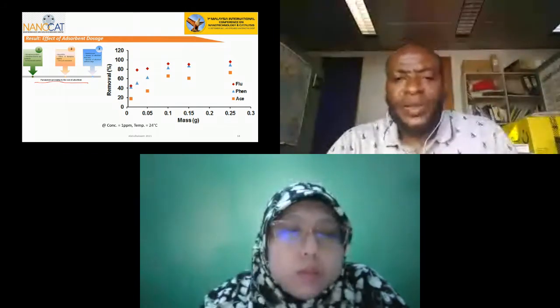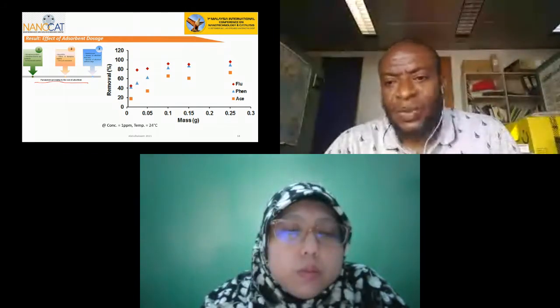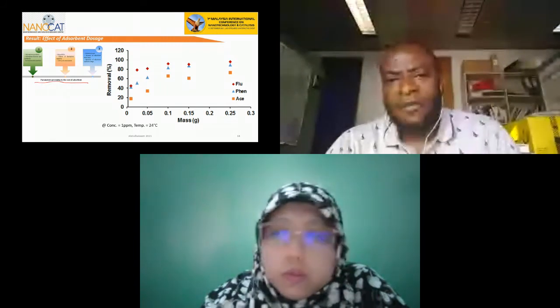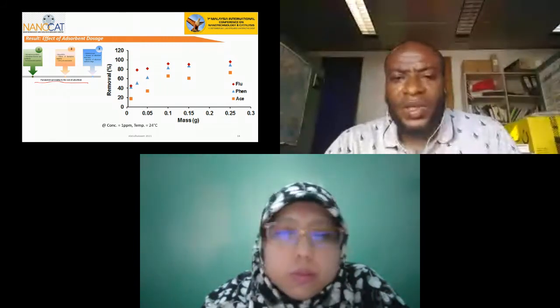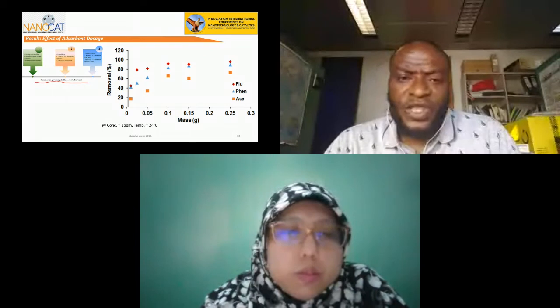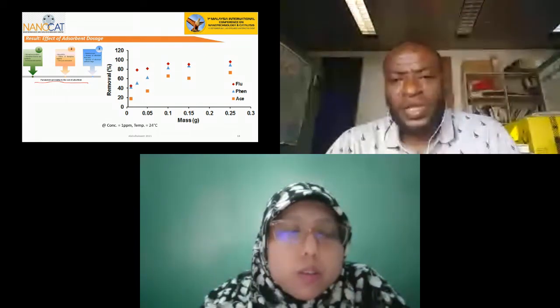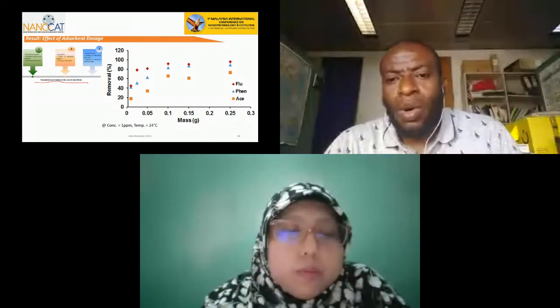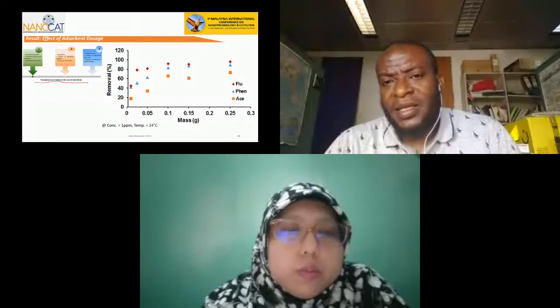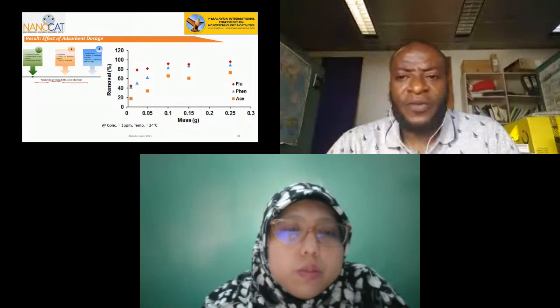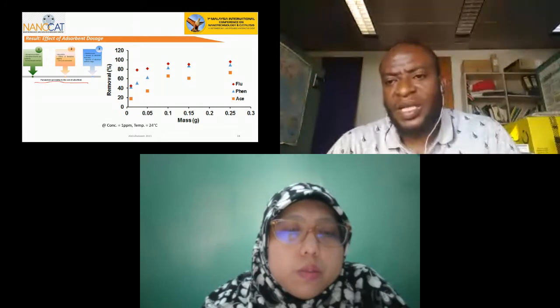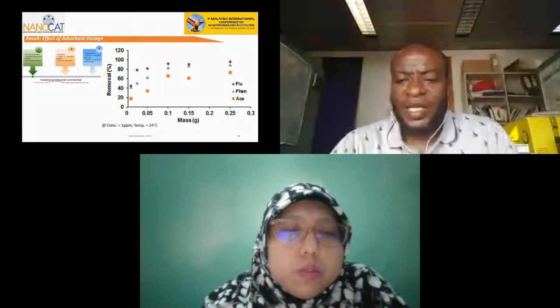Therefore, we varied the dose from 5 milligram to 300 milligram. And as we varied the dose, removal efficiency was increasing until it reached maximum at 100 milligram. And at this optimum dose, fluoranthene has the highest removal efficiency, followed by phenanthrene, followed by acenaphthylene.